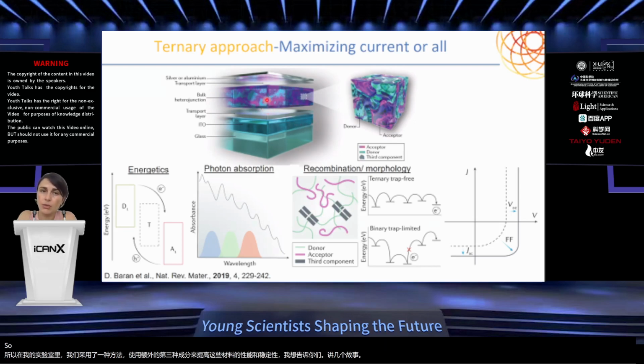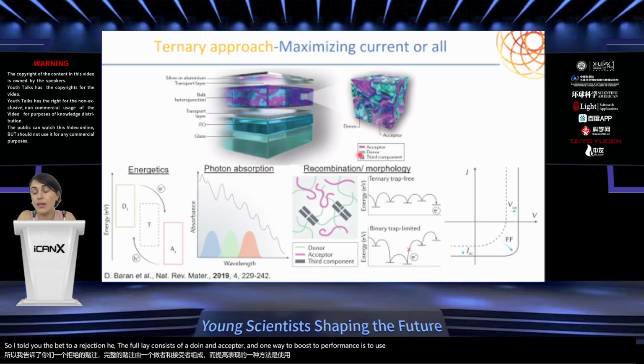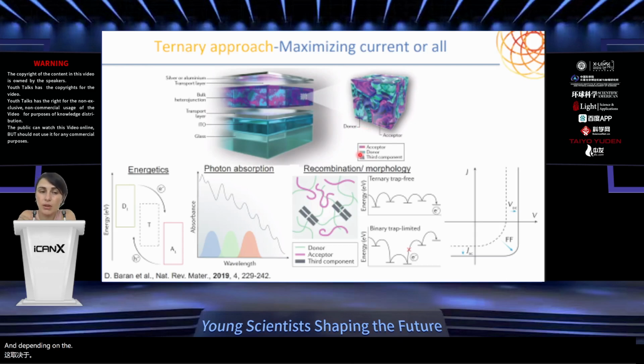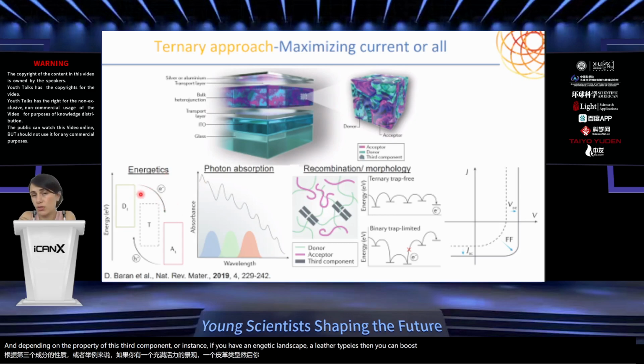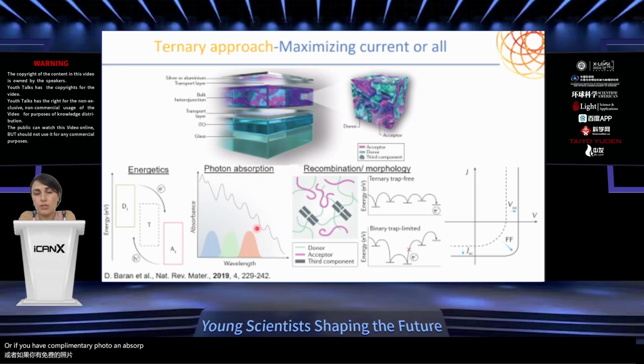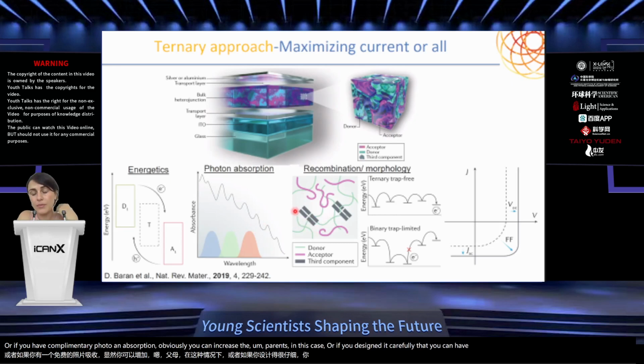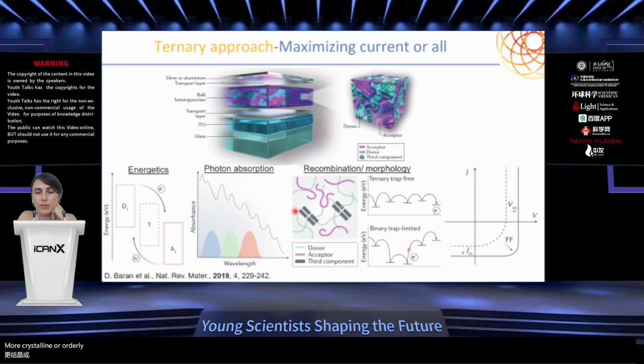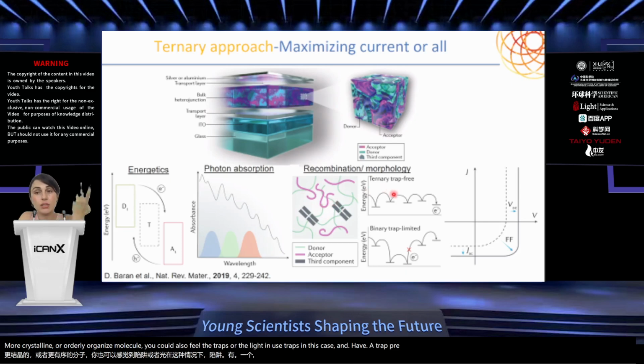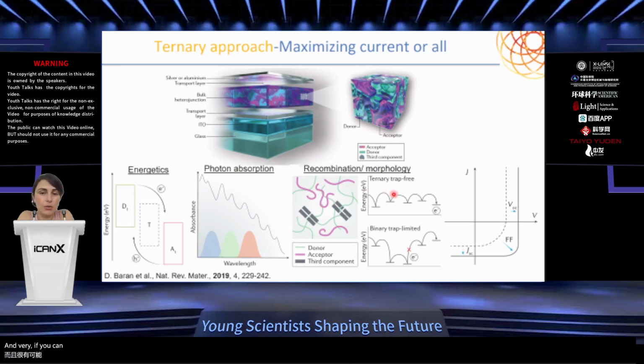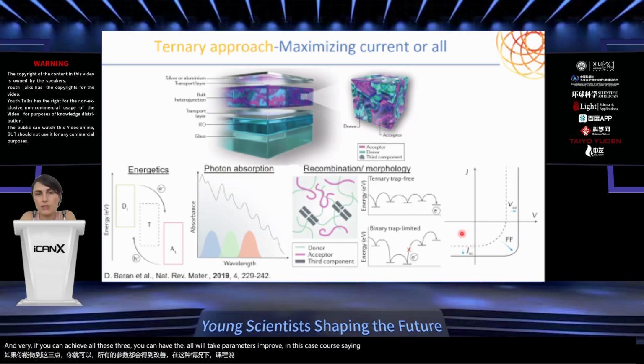I told you the bulk heterojunction here, the photoactive layer, consists of a donor and acceptor. One way to boost your performance is adding a third component. Depending on the property of this third component, for instance, if you have an energetic landscape with ladder type energies, then you can boost the voltage. Or if you have complementary photon absorption, obviously you can increase the current. Or if you design it carefully so that you have a more crystalline or orderly organized molecule, you could also fill the traps, or the light-induced traps, and have a trap-free system boosting your fill factor. In theory, if you can achieve all three, you can have all photovoltaic parameters improved. Of course, this is easy to explain.